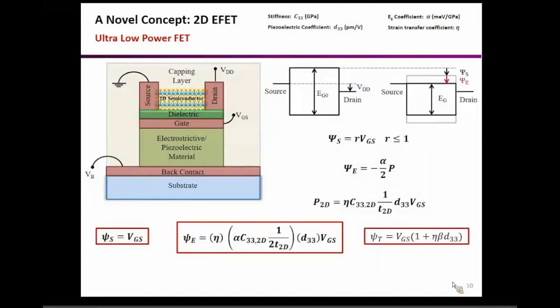Now let me try to explain a little bit about how this device actually operates. In fact, the simple diagram that I showed you may not be practically implementable, because these piezoelectric materials require higher processing temperatures, and you cannot integrate this piezoelectric on top of the 2D material, because the 2D materials are not that stable at the temperature where you grow or synthesize these PZT-type materials. So what we need to do is first grow this piezoelectric, and then on top of that we put our 2D transistor. Essentially, in this 4-terminal device, we have decoupled two actions. One is the EFET action, which is still our normal transistor, but on top of that we are adding an actuator action, or a mechanical action.